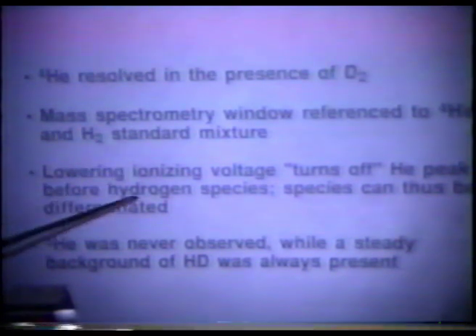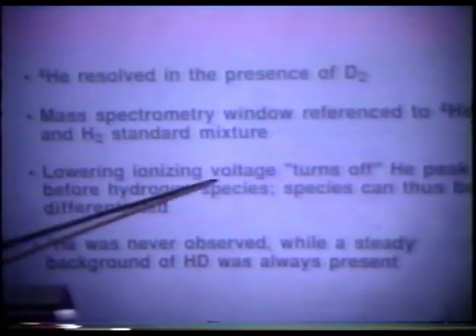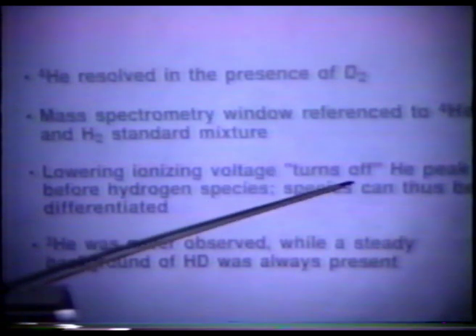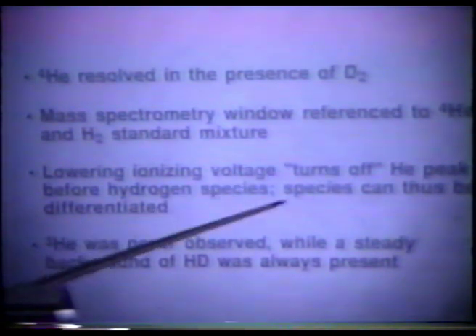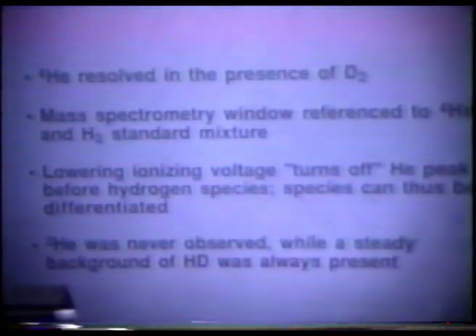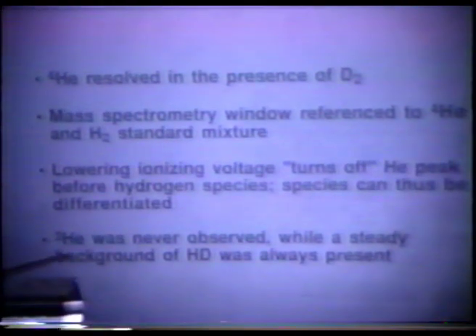We had some references. You could lower the ionization voltage if you had any question, and it would turn off the helium peak before it turned off the hydrogen peak. So you could distinguish if you had a question. We looked for helium-3 always in each experiment, but we never found it. Doesn't mean it wasn't there. It just means that if it were there, it was below our detection limit. It doesn't prove it was not there at all, however.